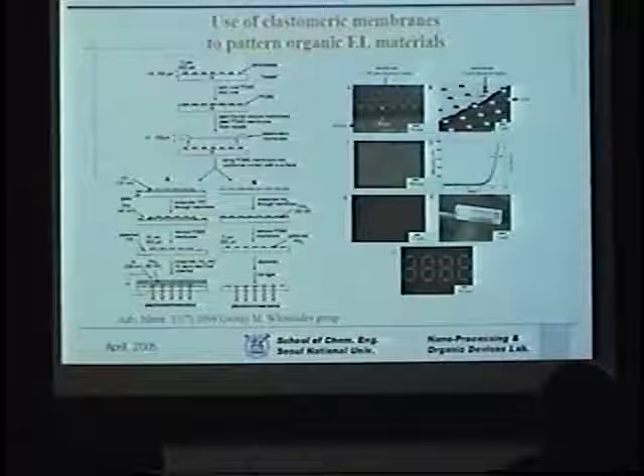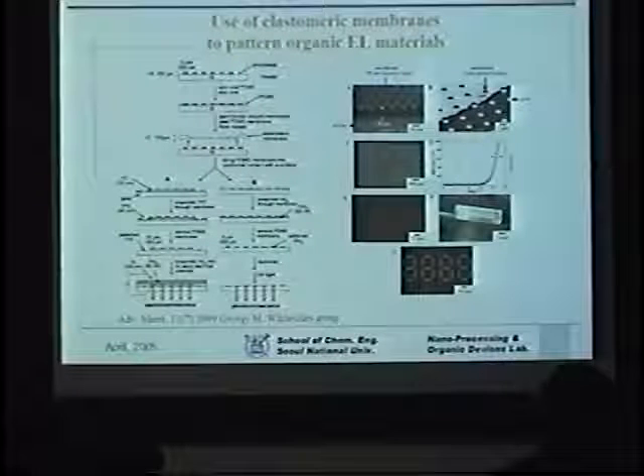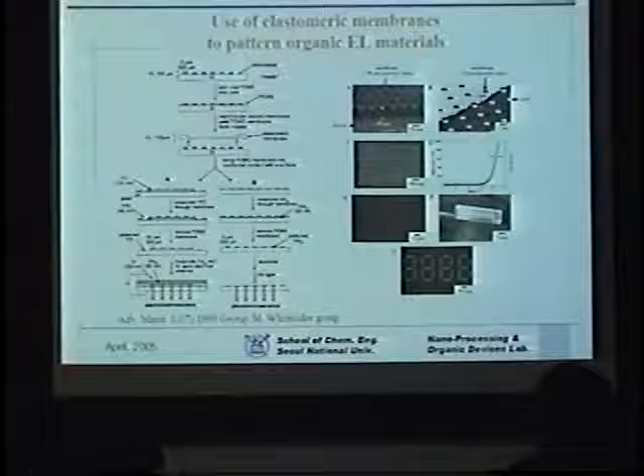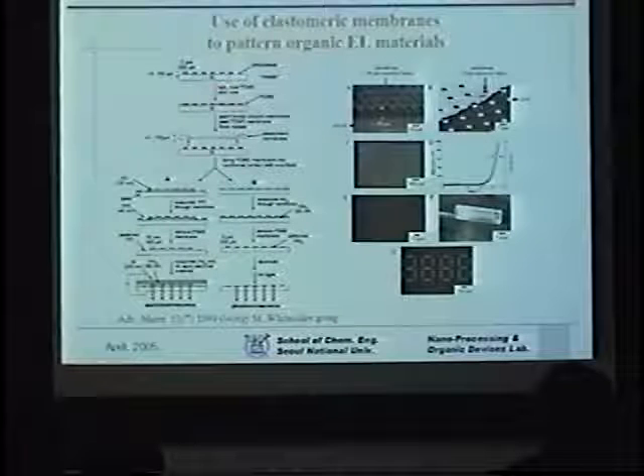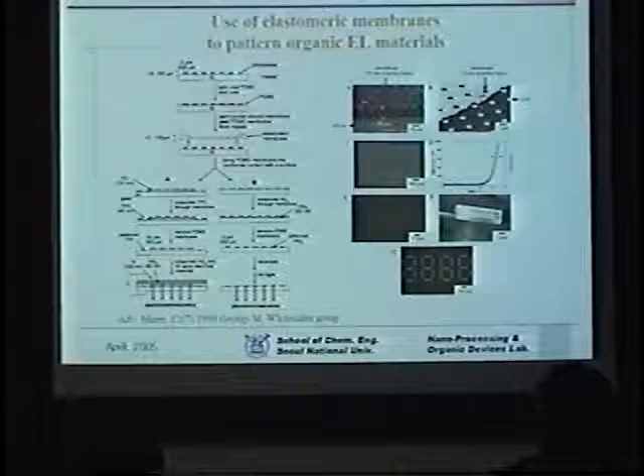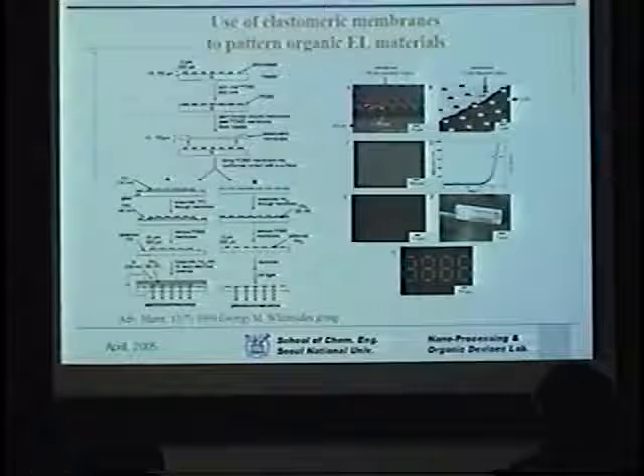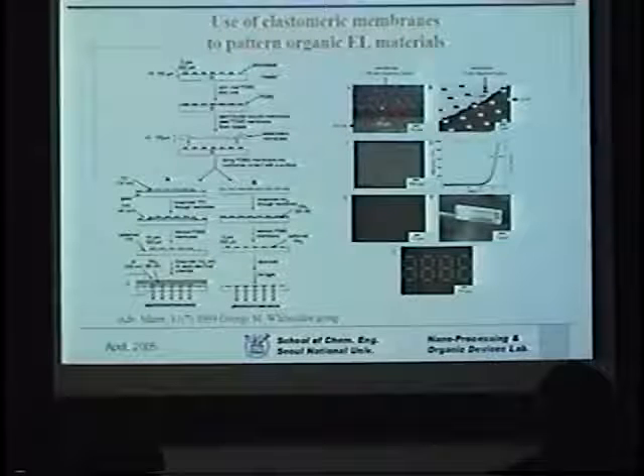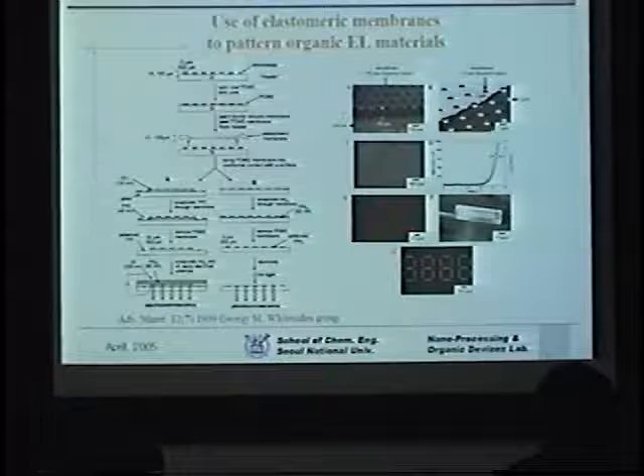Also, there were a number of efforts by Whitesides' group at Harvard. In this case, he used a PDMS mold, or polydimethylsiloxane mold. And this perforated membrane essentially acts as a shadow mask, but this time in contact mode, so you do the deposition and get what you want.